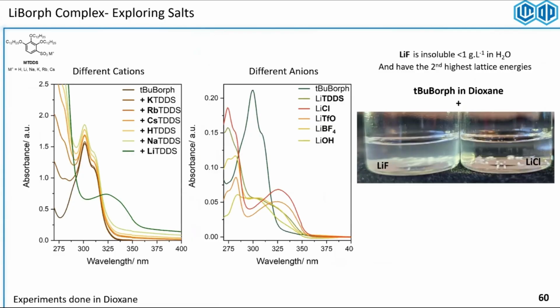It was such high binding to the lithium that we could add lithium fluoride, one of the most insoluble lithium salts on Earth, and just adding an etheric solution of macrocycle on top of that, we could extract the lithium from the surface of these solids and turn it into a sort of gel, because the fluoride was also interacting with our porphyrin at the time. But this also happened for lithium chloride. We could look at the solution of the porphyrin and then add any type of different crystals of lithium salts.